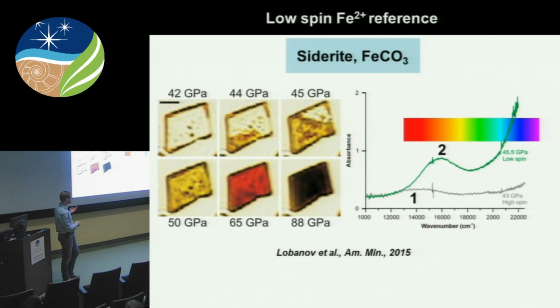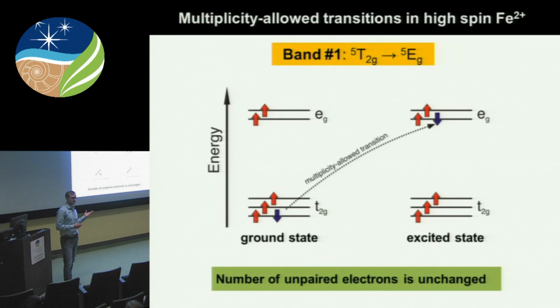So the high-spin siderite has only a weak absorption band at approximately 14,000 wave numbers that I marked by 1 here. However, low-spin siderite has a more intense absorption band at 16,000 wave numbers. And this absorption band is actually characteristic of low-spin Fe2+. Also, you can see a dip in absorption at green wavelengths, and this is exactly why this mineral turns green upon the spin transition. So we do understand these absorption bands in terms of spectroscopic selection rules.